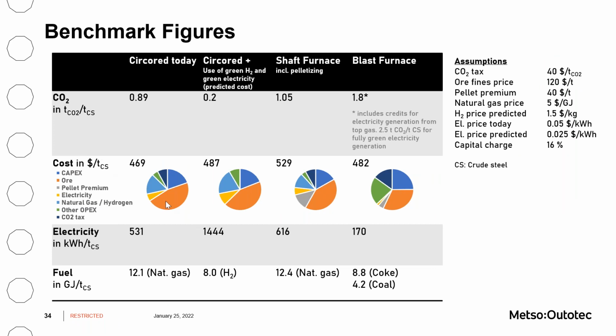The table here shows the results of a techno-economic analysis. The model we used for this is based on some assumptions shown here on the right. Worthwhile to highlight is the price for carbon taxation of $40 per ton, the fine ore price of $120 per ton, and the pellet premium price of also $40 per ton. These figures are rather conservative, I would say.